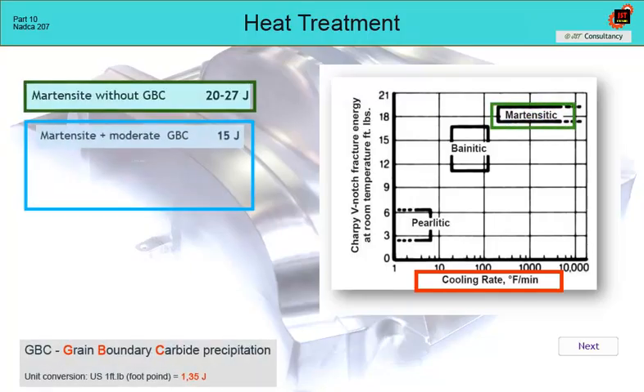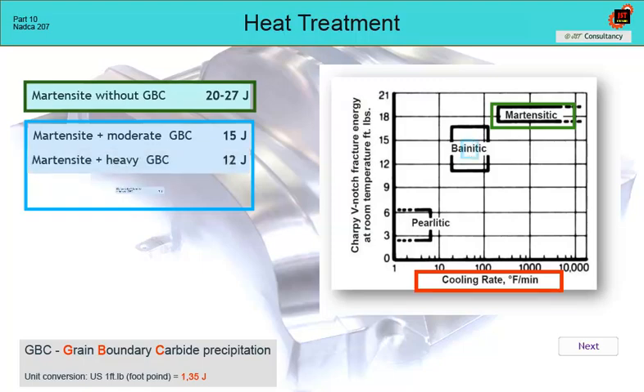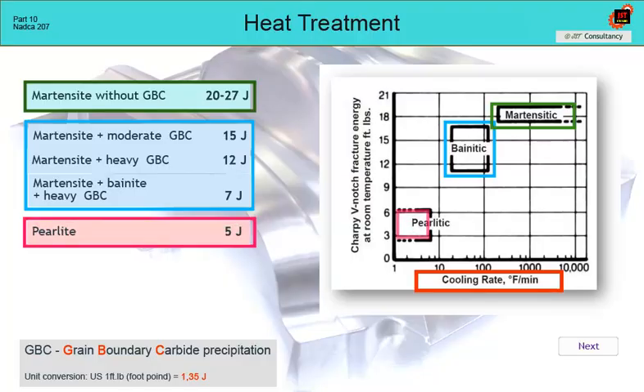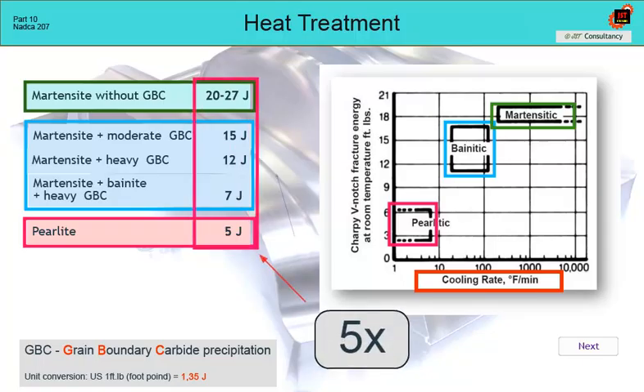Indirectly from this figure it follows that after quenching, we can achieve values of up to 20 to 27 joules of impact strength, as well as only 5 joules. An improperly conducted hardening process can therefore lead to almost a 5-fold deterioration of the material's mechanical properties.